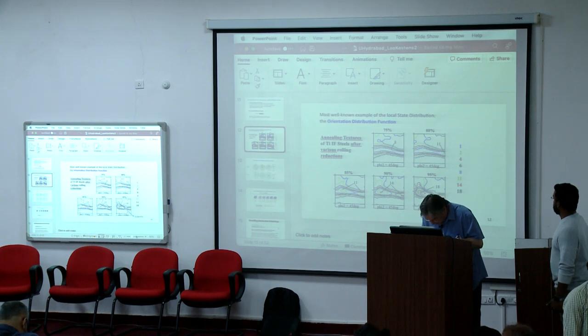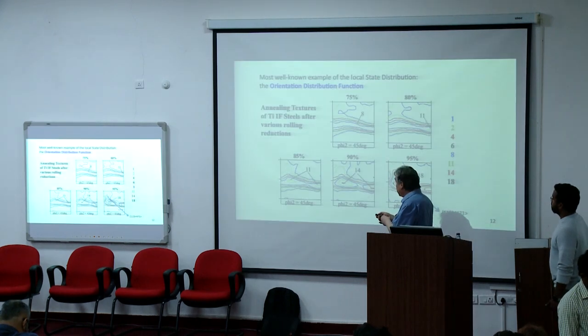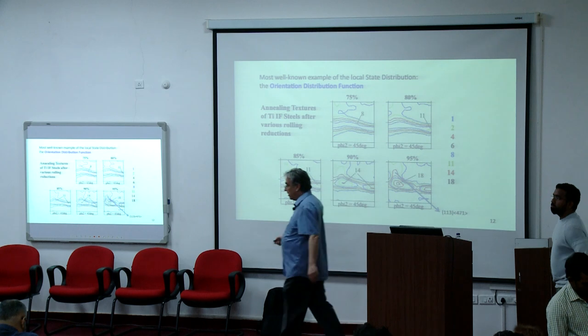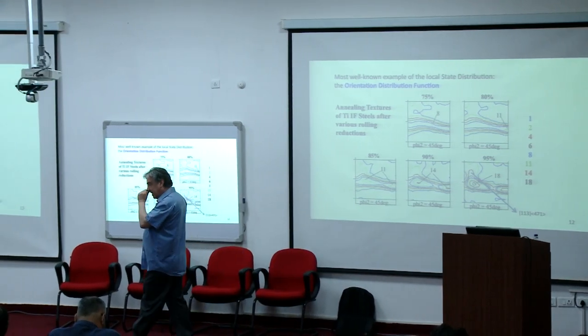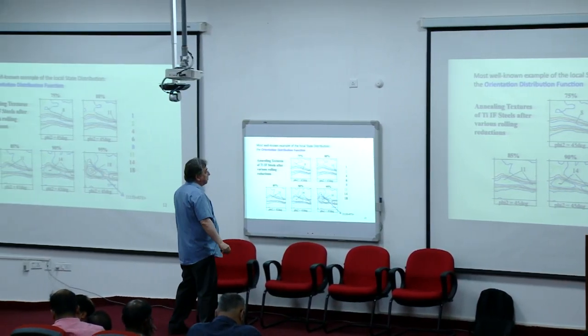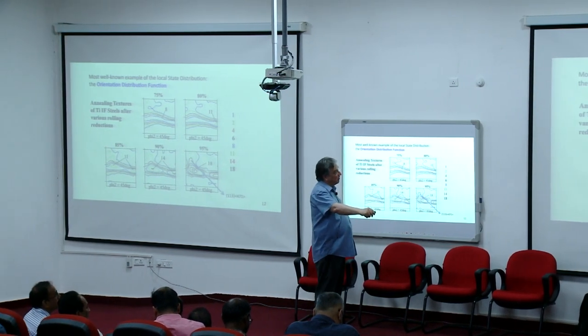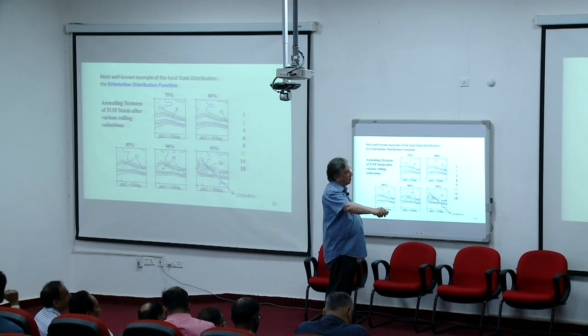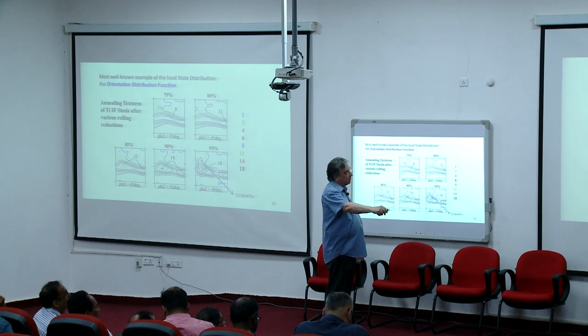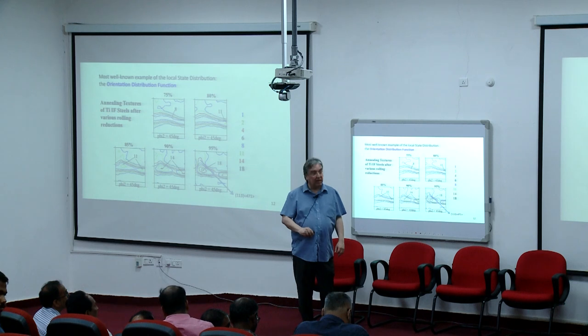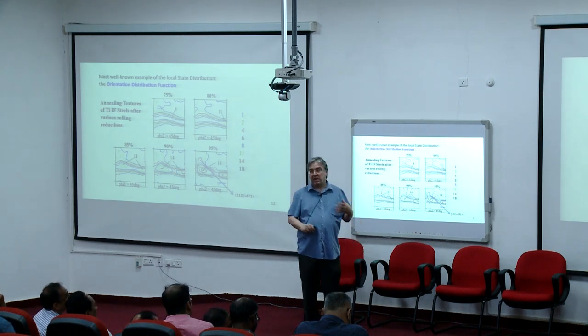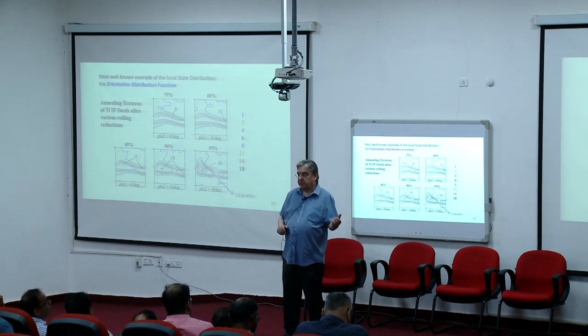I gave here some examples. This is of textures of an IF steel, interstitial free steel. The good deep drawability properties result from having all crystal orientations on this line. And if you have a perfect line on this, you will have no ears. That's why this steel is especially made by the steel industry to obtain good drawability, and good drawability means